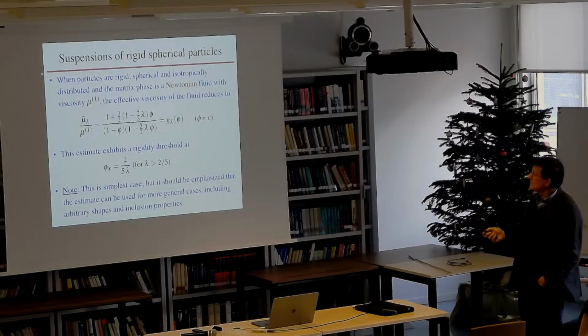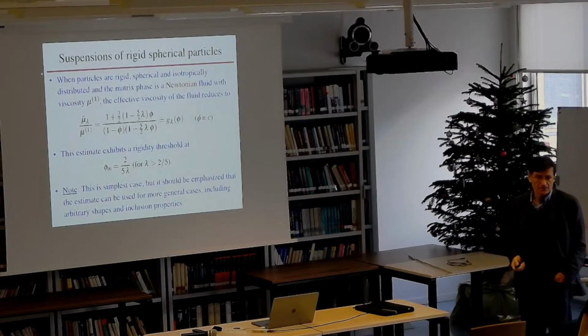So what happens if you try the simplest case, an isotropic distribution of spherical rigid particles? You get a result that looks like this. The effective viscosity divided by the viscosity of the suspending material, a Newtonian fluid if you like, is given by this formula here that involves phi. Sorry about the change in notation - phi is the volume fraction, and lambda is this interpolating parameter.